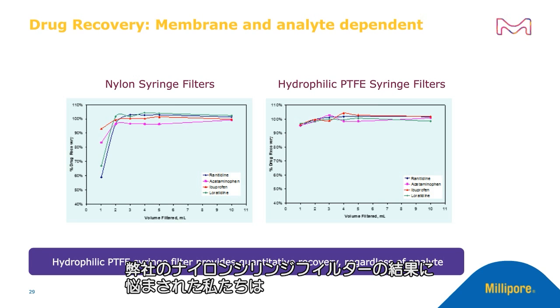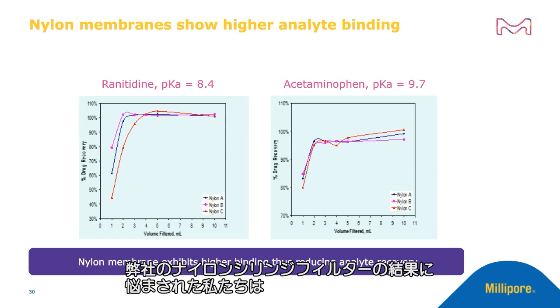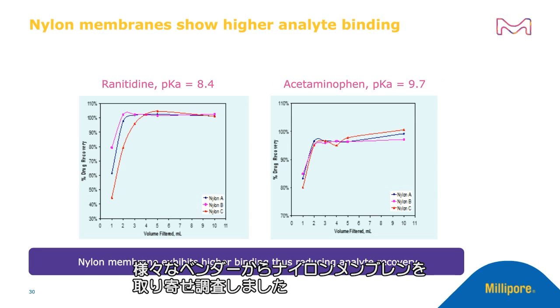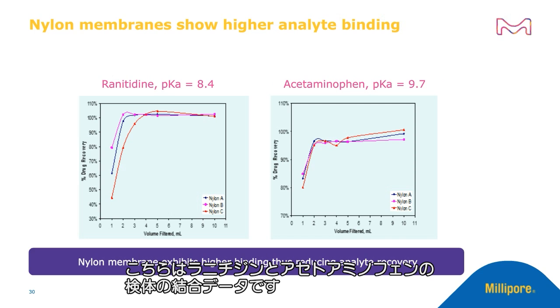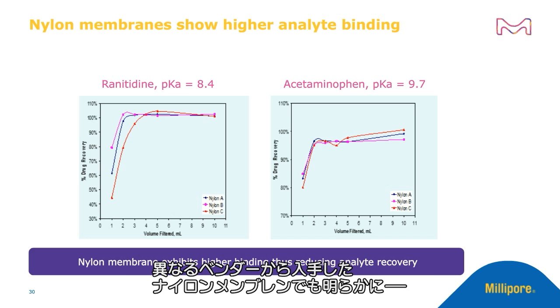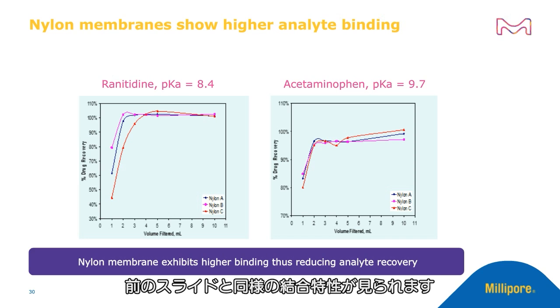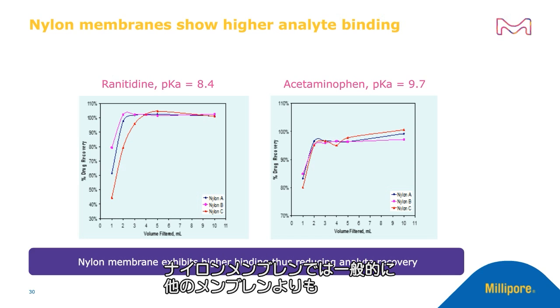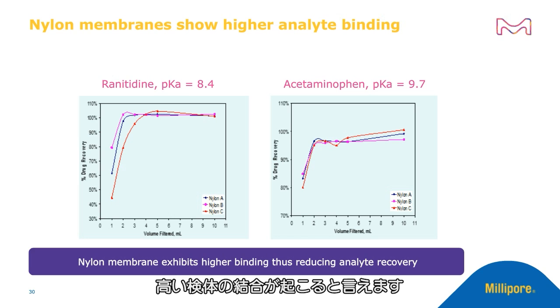When we saw these results with our Millipore Sigma nylon syringe filters, we were concerned. So we started looking at the nylon membrane from various vendors. And we are showing data here for analyte binding for ranitidine and acetaminophen. You can clearly see that even for nylon membranes from different vendors, you can see the same binding behavior similar to what we saw in the previous slide. So nylon membrane in general tends to show higher analyte binding compared with other membranes.